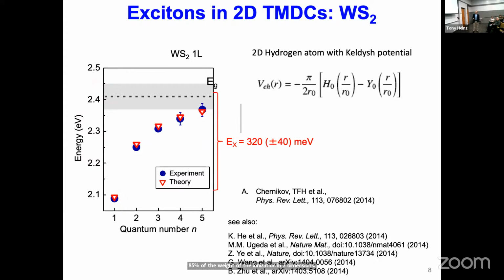So you might ask, why does this look so different? And the answer is that you have to still take into account dielectric screening of a thin layer. So it's not a homogeneous reduction. And in a simple analytic approximation, that gives you the so-called Keldysh potential. That's the electron-hole, the charge interaction in a thin sheet in 2 dimensions. And if you put in this somewhat complicated looking potential instead of a 1/r potential, then you can predict these excited states quite nicely. So that's a kind of effective Hamiltonian approach to the problem, but it describes what's going on quite well. And you can see here that the extrapolated binding energy is really quite significant.